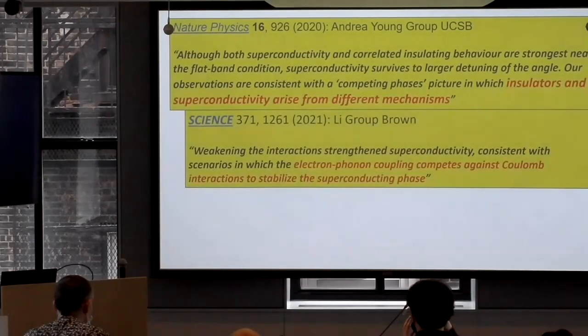But there is a direct experiment from the group of Li and Brown, where he really changed the gate distance in several samples. And what he found is weakening the interaction strengthens superconductivity, consistent with scenarios in which electron-phonon coupling competes against Coulomb interaction stabilization. Now, this paper has an interesting history. If you go to arXiv and look at the first posting of this paper, it came to exactly the opposite conclusion. Their conclusion was that it's electron. They found that TC is enhanced when screening goes down.